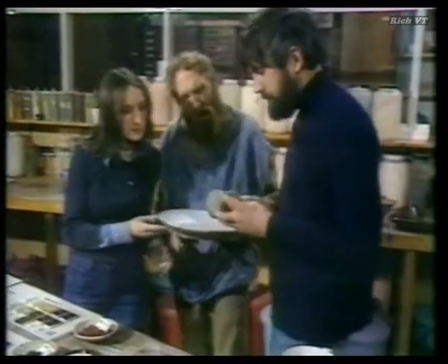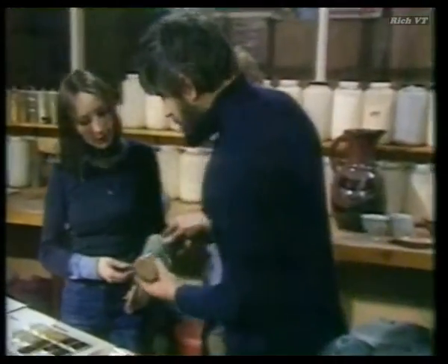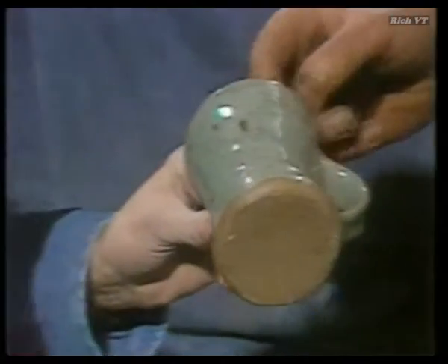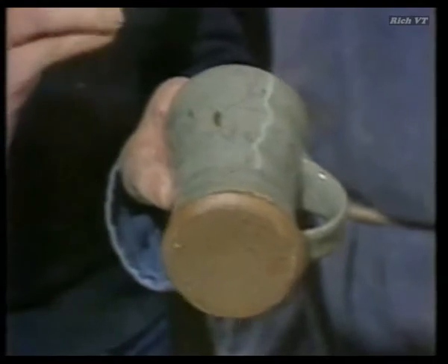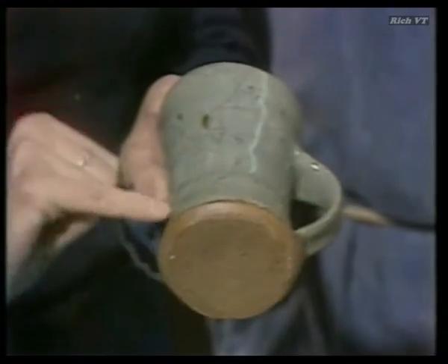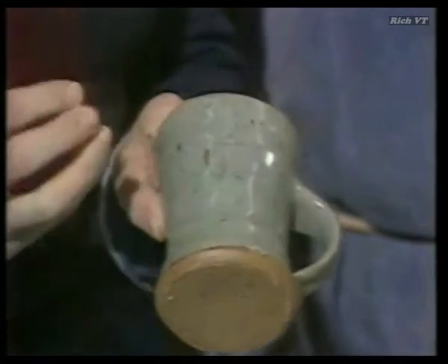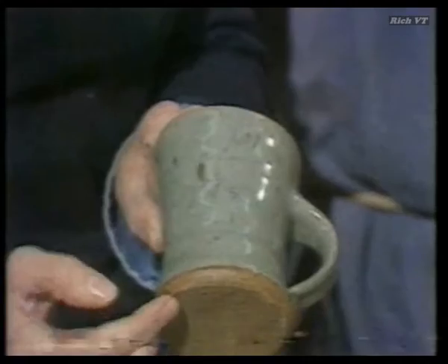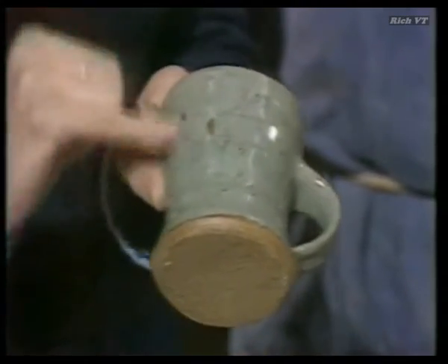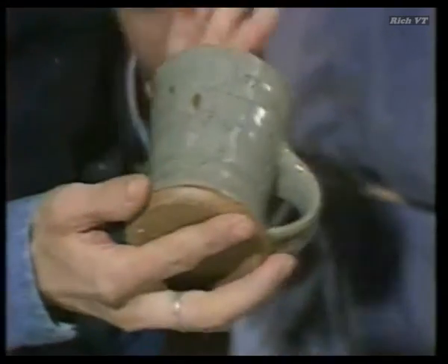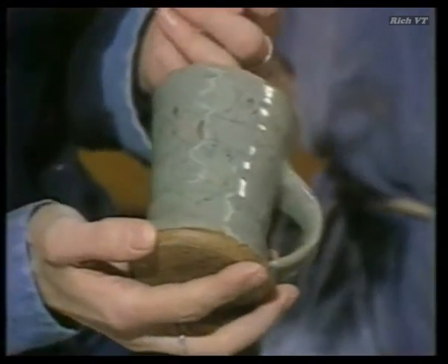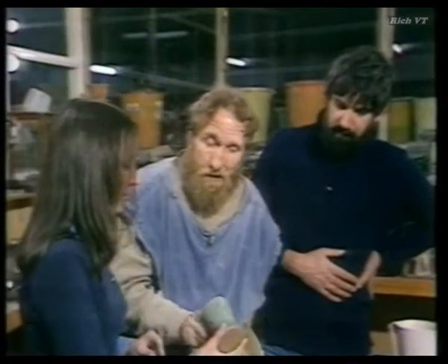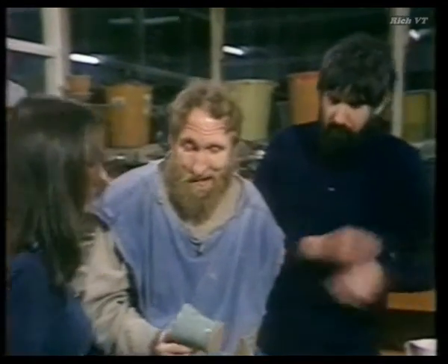What about that one, Wally? Well, this one we're all familiar with, I think. It's crazing. Lynn, can you tell us about crazing? Yes, this is a very common defect. It occurs when the clay and glaze haven't shrunk to the same extent in firing. In this case, the glaze has contracted far more than the clay of the pot, and so the glaze has cracked. The only way to cure this is to alter the composition of the glaze. It's a very interesting effect, and of course it may mean that one man's defect is another man's special effect.